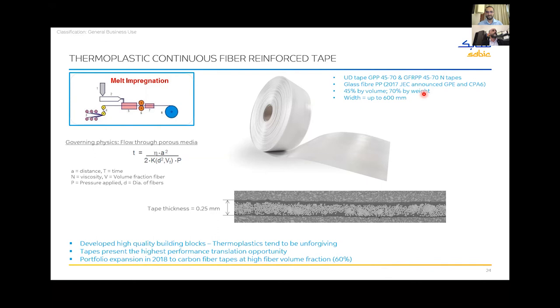You've got fibers that are very densely packed. Sometimes if you look at carbon fiber, 12,000 filaments, 24,000 filaments, 50,000 filaments coming together, very dense fibrous preform, and you're trying to push into the fibrous preform a very viscous fluid like a thermoplastic. And so we oftentimes lean on flow through porous media from Darcy's law, created for soils many, many years ago. It actually works quite effectively when we look at flow through porous media and trying to get good impregnation of these tapes to make high quality materials.